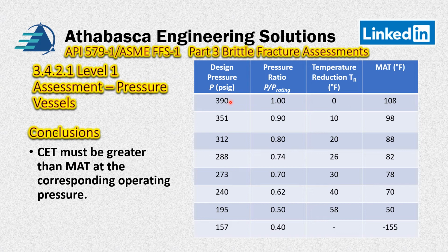So now, for example, if they need to operate at a lower temperature, one strategy available in your toolbox now is that you can reduce your pressure in your unit. So for example, if you reduce your pressure all the way down to 240 psig, which corresponds to a pressure ratio, you can take advantage of the pressure ratio and reduce your temperature by 40 degrees to get yourself down to 70 degrees Fahrenheit. And now you can drop your CET in certain cases. So a very, very useful curve for making operating decisions to improve safety.